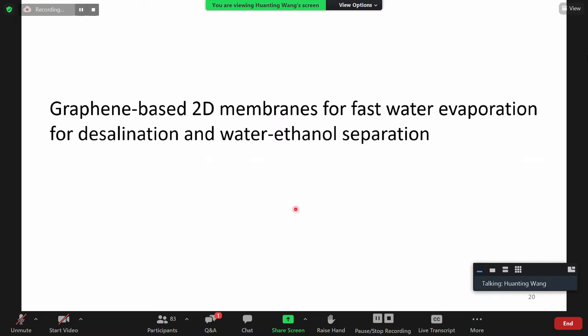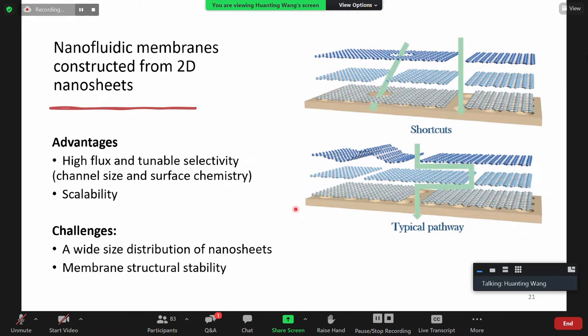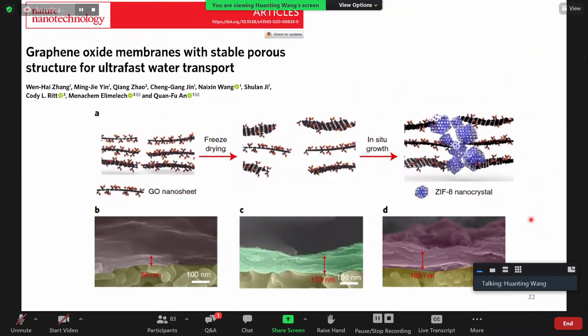Now turning to graphene-based membranes — there's a lot of work in this space. With 2D nanosheet-based membranes, the molecular and ion transport pathway could be through the nanosheet itself or through the interlayers. These different pathways bring complexity to ion and molecular transport. For example, GO nanosheets sealed with ZIF-8 — which widened the interlayer spacing — resulted in a membrane that became much more stable in water.